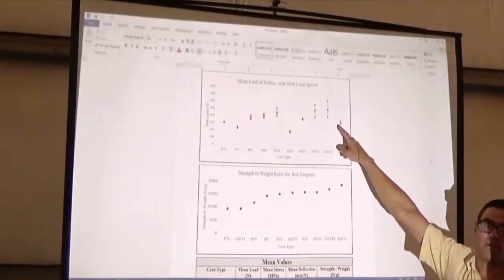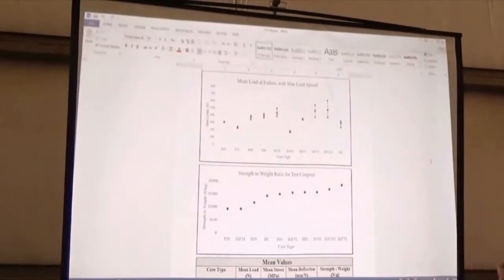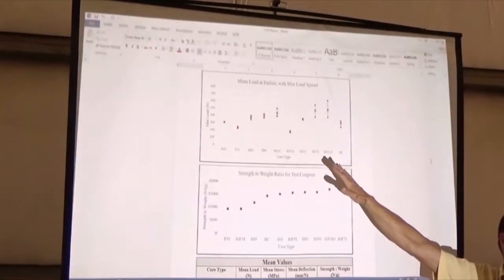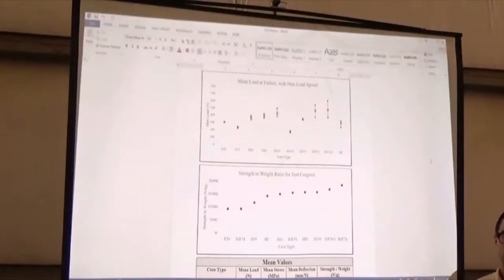Honeycomb is kind of a middle-of-the-pack performer, and the reason for this, at least from what I can understand in my study, is that when you're doing a really thin face sheet on honeycomb, and by thin face sheet I mean 1 or 2 layers of carbon, the space between those cells is large enough that you get dimpling, and basically you're getting buckling of the face sheet. So the foam works better for really light face sheets because it's a smooth, solid surface. And it also has micro buckling, but not to the same extent that honeycomb does.